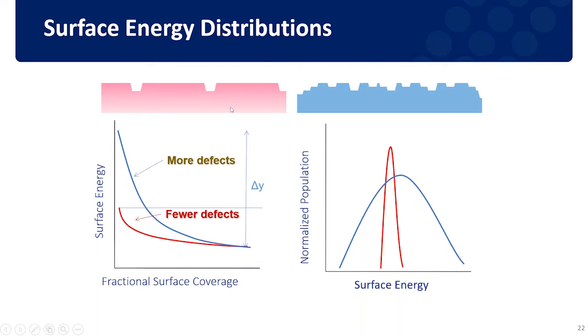So for example, here we have the red surface, which has less variation and is more smooth, or less rough, than the blue surface. Then we have less variation between the high energy sites and the low energy sites. Whereas for the blue surface, we have more defect sites on the surface, so we can have a really large variation between the high energy sites and the low ones. So the surface energy distribution of this surface is also wider. So here we can tell from the surface energy distribution which sample is more heterogeneous and which sample is more homogeneous.